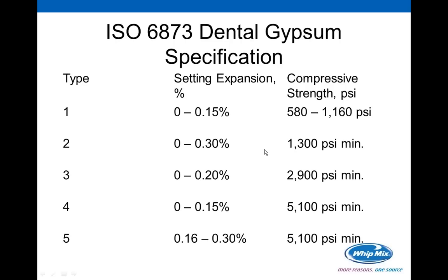If we take a look at some of the other specs that are going on, we'll find that in the ISO specification 6873, we can talk about how they're broken into these 5 types of stone. You see type 1, remember we said that those type 1s and type 2s were generally plasters. These will have a setting expansion anywhere from 0 to 0.15 in the case of the type 1, or from 0 to 0.3 in the case of a type 2. And they have a compressive strength minimum. This is a minimum value that's here in the right-hand column. Type 1 somewhere between 580 to 1160, and type 2s need to be 1300 psi minimum.